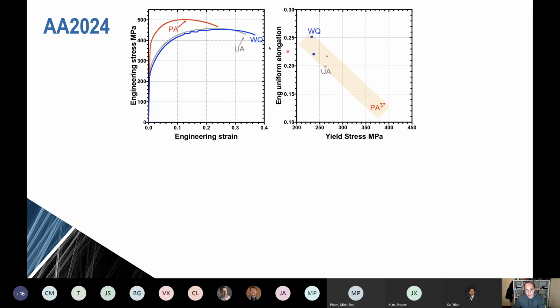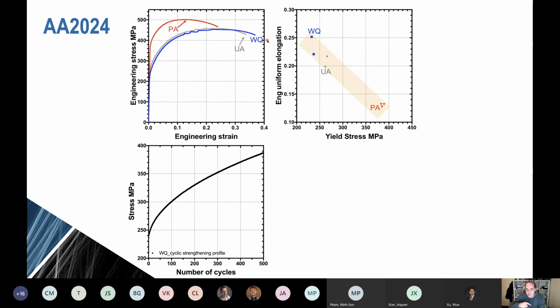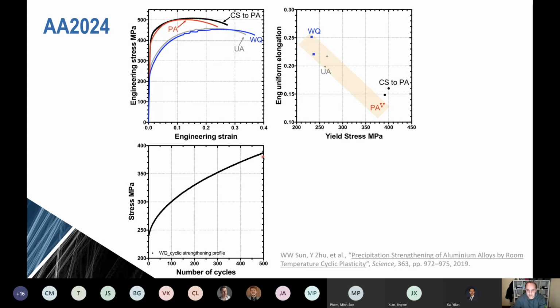So if we take a water quenched material and now subject it to the sort of cyclic plasticity that I was just referring to, and remember the idea here is to inject vacancies into the material to drive mass transfer, which can occur at room temperature in aluminium alloys, and try then to have a decomposition of the solid solution. If I apply this sort of profile and I do that for 500 cycles, then I take the sample off and I do a tensile test, this is what I get.